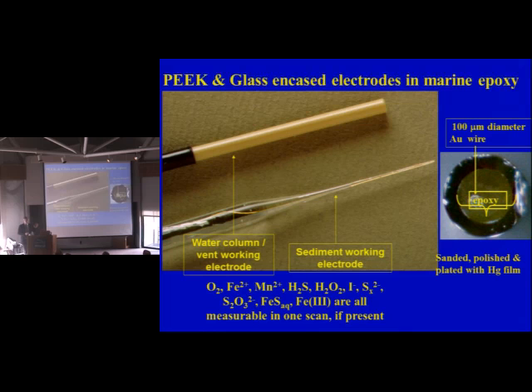Never use alumina. If you really want good data, always use diamond. It's harder, gives you a better finish, and then it's better for the mercury film. Notice I just said mercury film. So we actually coat this with mercury. The total amount of mercury on this tip is 10 to the minus 10 moles, to give you an idea. If it were not for the mercury, we could not measure the metals, iron and manganese in particular, because they reduce at very negative potentials.